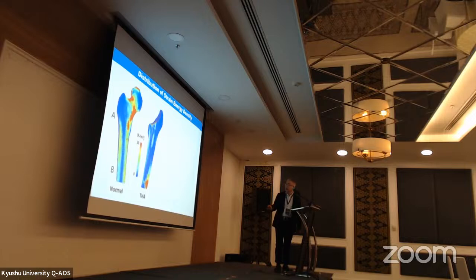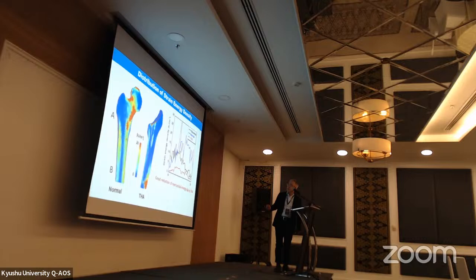So then if I plot this energy distribution from A to B, we can get this kind of graph. The blue one is normal bone, and the red one is THA bone. Okay, we can see a large reduction of mechanical energy. So this causes problems. This is called the stress shielding effect. Then this patient may have a severe reduction of bone density.